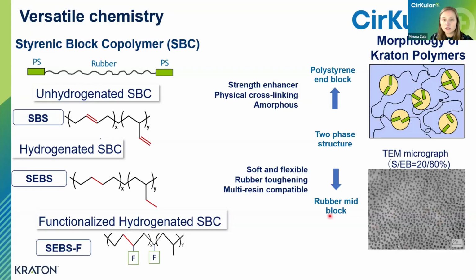These hard domains act as physical cross-linking points, giving the material the elasticity and strength of a cross-linked elastomer, without the need for chemical curing. At room temperature and below, SBCs exhibit excellent elasticity, high elongation, tensile strength, and the ability to absorb a lot of impact energy. The products can be melt processed like thermoplastics, such as polyethylene or polypropylene, and this duality places them in a unique category known as thermoplastic elastomers.